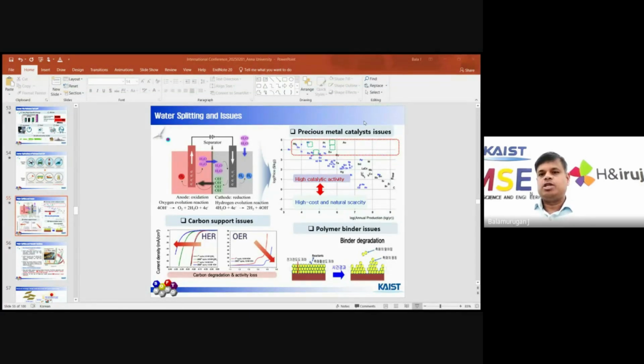When we go for these precious materials in industrial applications, we face this kind of problem of polymer degradation, because we need to fabricate the electrode over some current collectors using this kind of polymer. We cannot coat the commercial platinum catalyst or ruthenium directly onto the substrate. This is the big issue.